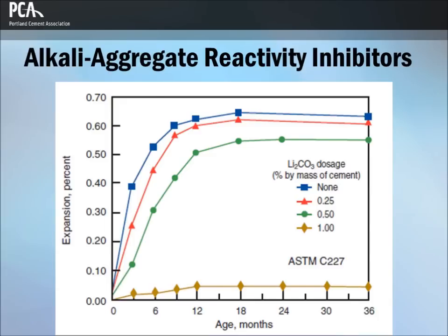Lithium-based components, when used in sufficient quantity, are capable of inhibiting damage due to alkali silica reactivity, or ASR. ASR gel has a great capacity to absorb moisture from within the concrete pores. If lithium nitrate is used as an admixture, the pore solution will contain lithium and nitrate ions in addition to sodium, potassium and hydroxyl ions. The resulting lithium bearing reaction product does not have the same propensity to absorb water and expand.